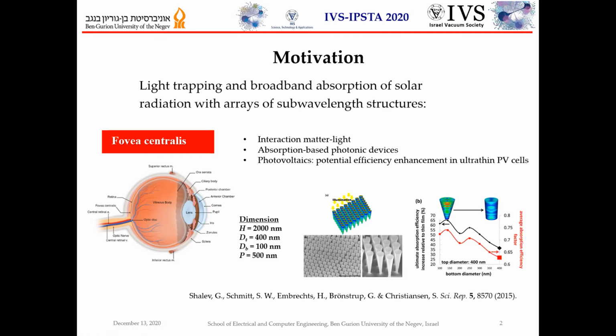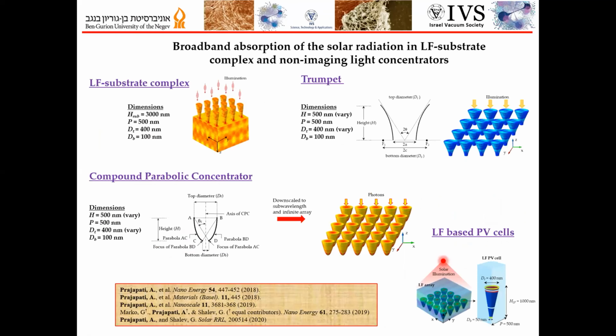They showed 65% absorption enhancement compared to a silicon film of identical thickness, and also showed power conversion efficiencies that are 60% higher than those of optimized nanowire arrays of the same thickness. Other motivations of my work are light matter interaction, absorption based photonic devices, photovoltaic applications, and potential efficiency enhancement in ultrathin PV cells.